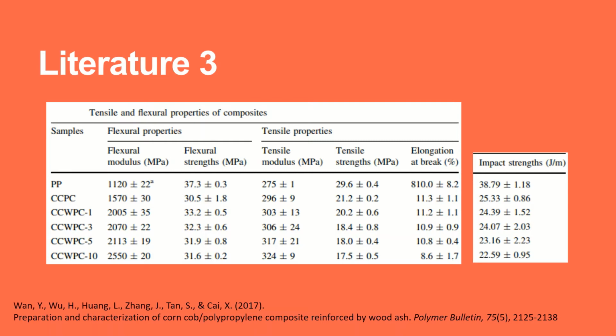First, the flexural modulus increases when the amount of wood ash is increased. This is an indication that wood ash serves as a physical cross-linking point which hinders the motion of polypropylene and higher stiffness of corn cob flour compared with polypropylene. The flexural strength decreased when corn cob flour was added into the composite. This could be attributed to the weak interaction and low compatibility between hydrophilic corn cob flour and hydrophobic polypropylene.